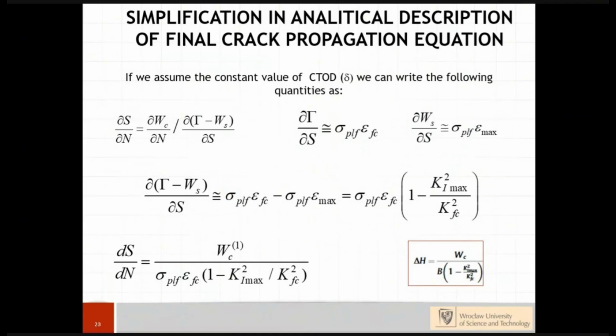And finally, it is something like this. So we can introduce a new energy parameter, which is based on the dissipated energy in each cycle of loading. And of course, B is the thickness of the specimen, as well as K1 max. So it is, let's say, the trace of the loading, and of course, the critical stress intensity factor.